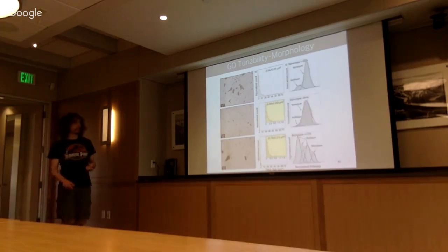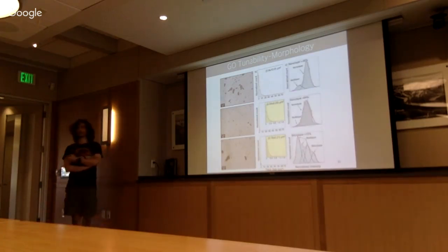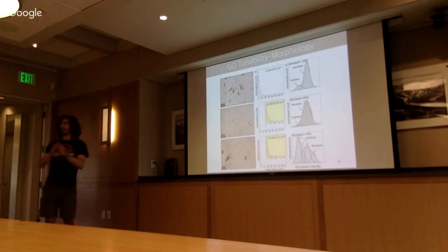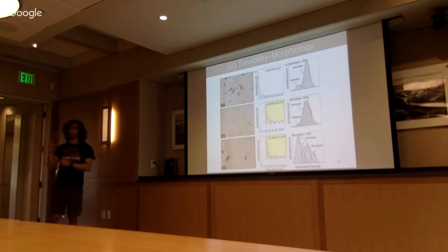And then we push this further. With other imaging techniques, we can also count the percentage of monolayer versus multilayer material. And this is really important because when you're producing graphene oxide, ideally you want all flakes to be monolayer, but not all the processes are perfect. So you end up having some material which is multilayer. But with these imaging techniques, we can check the quality of the material.